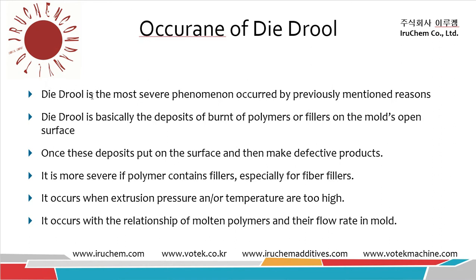Die drool is the most severe phenomenon caused by the previously mentioned reasons. Die drool is basically the deposit of low molecular, burnt polymers or fillers on the die's open surface. Once the deposit — the die drool — is put on the surface, it makes the product surface defective. It is more severe if the polymer contains fillers, especially fine fillers. It occurs when the extrusion pressure or temperature are too high, because the molecules burn more easily and become low molecular weight very easily.